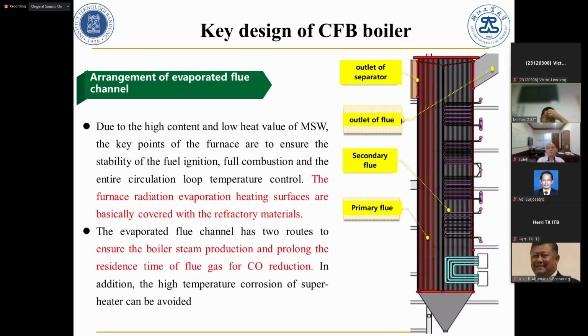So this is the arrangement of the evaporative flue channel. The furnace radiation evaporating heating surfaces are basically covered with refractory material. So in the furnace, we reduce the heat exchanger. We hope the heat exchange happens later, so it can increase the incineration or oxidation reaction times. So 3T plus O: time, temperature, turbulence, and oxygen. So we use the heat exchanger behind instead, which will increase the reaction temperature and reduce the CO.